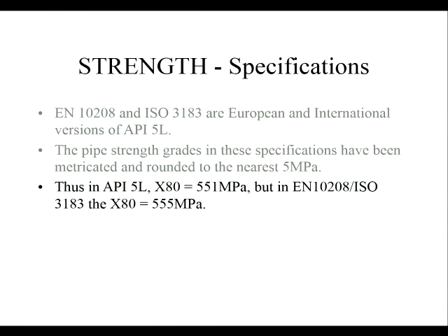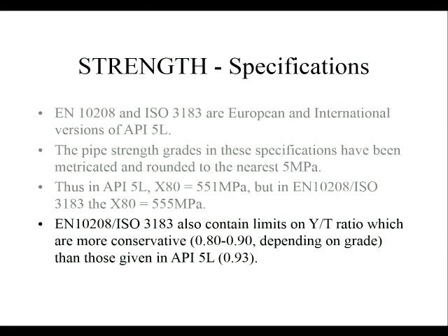So if you take API 5L X80, if you work out what that is in terms of KSI and then convert that into megapascals directly, you'll get 551 megapascals yield strength. But if you look at the international standards, the standard for X80 is 555 megapascals. So it's nearly the same. And frankly, it doesn't really make a great deal of difference when you do the calculations. Because if you're worried about 4 megapascals on 550, there's something seriously wrong with the design process.